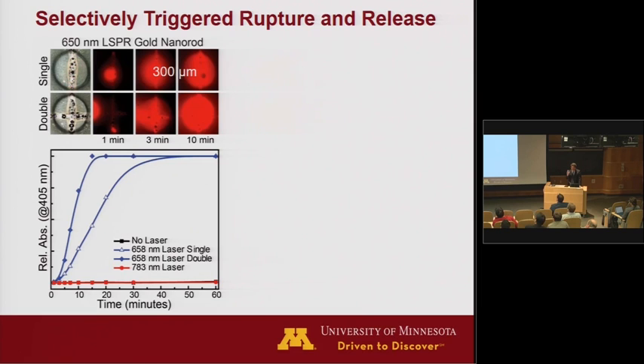What happens is the laser wavelength is tuned to the shape of the rod, so it heats up those rods. The rods melt the polymer shell, and then they form a hole in that shell, and then the contents from the core release through that hole. Okay, and what you can see here is if you raster scan it once or twice, that changes the kinetics of release, but the actual thermodynamics of the release are diffusion controlled.